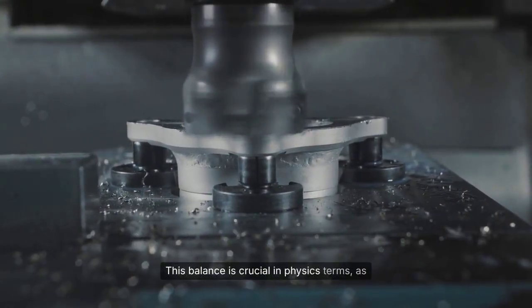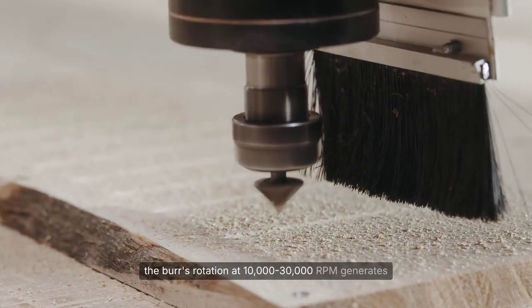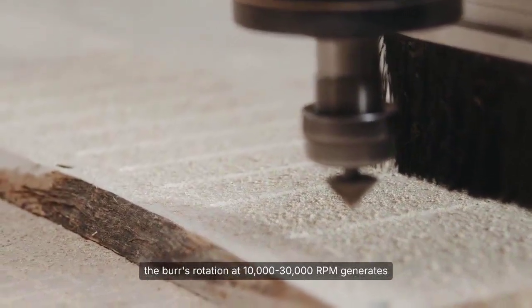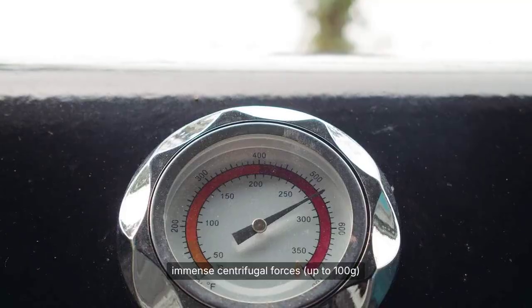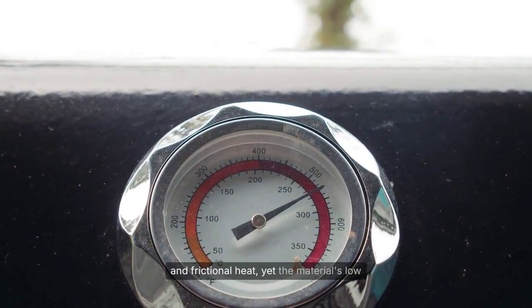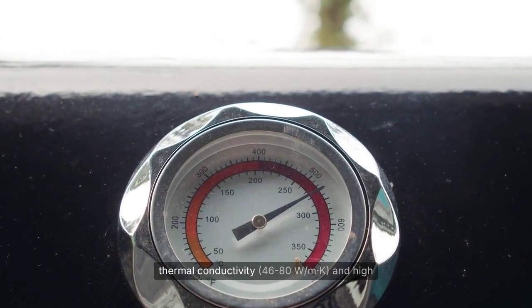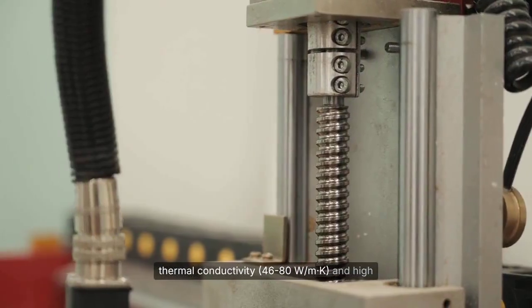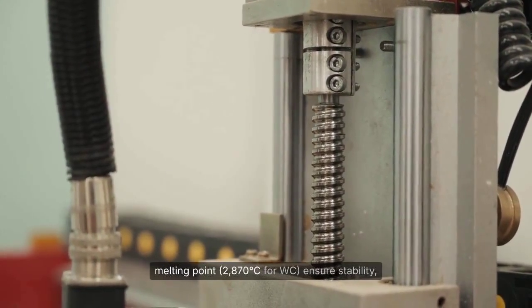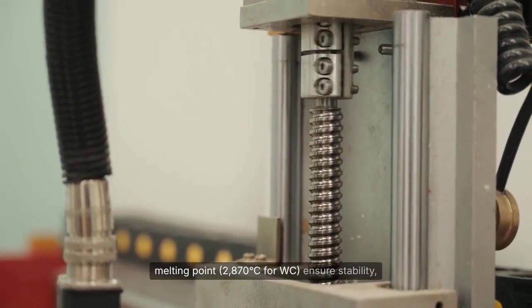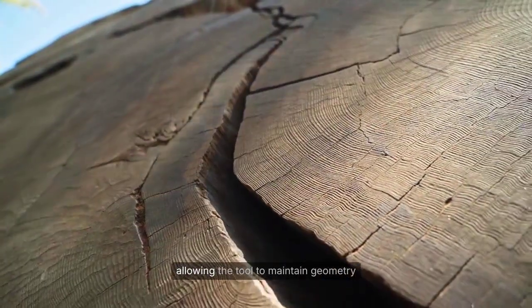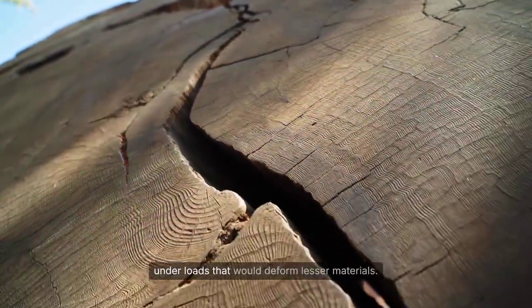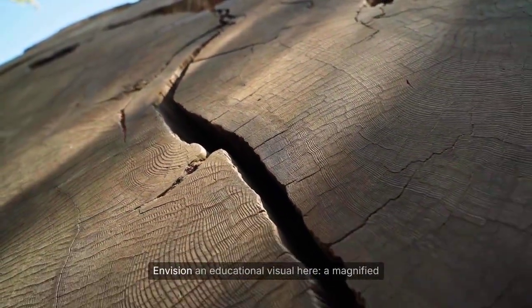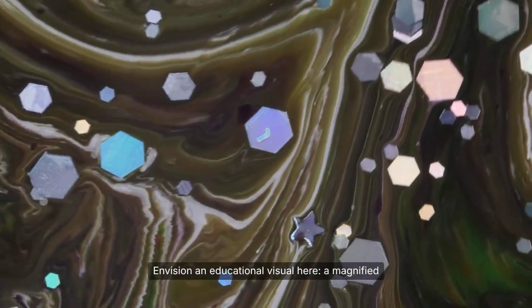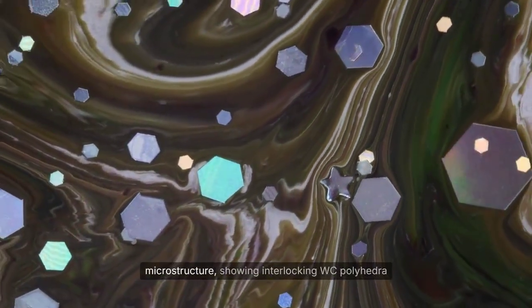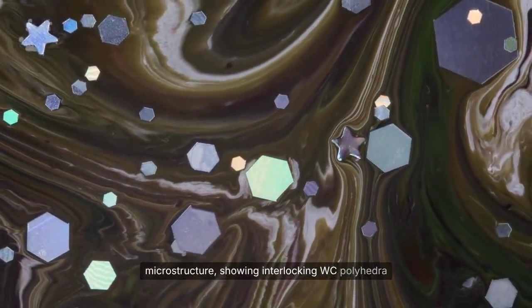This balance is crucial in physics terms, as the burr's rotation at 10,000 to 30,000 RPM generates immense centrifugal forces, up to 100 G, and frictional heat, yet the material's low thermal conductivity, 46 to 80 watts per meter Kelvin, and high melting point, 2,870 degrees Celsius for WC, ensure stability, allowing the tool to maintain geometry under loads that would deform lesser materials.